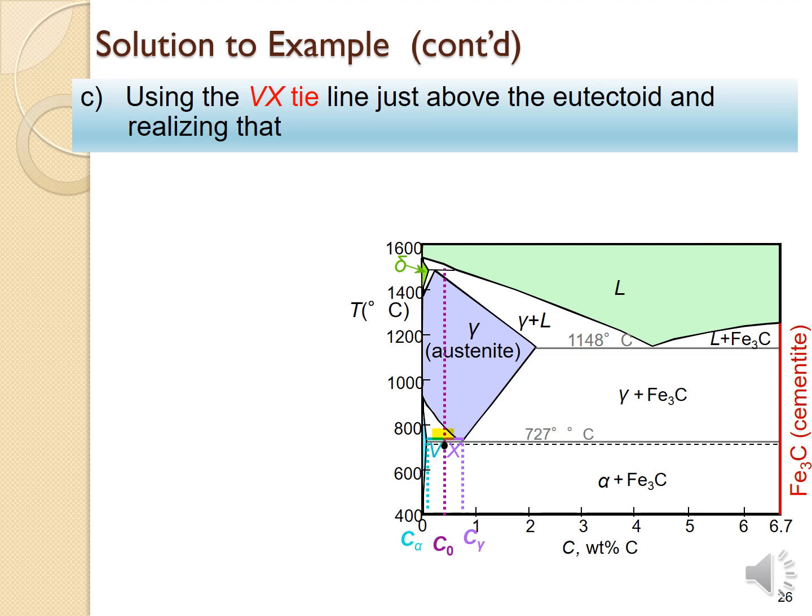Because during the eutectoid reaction, all of the austenite will transform into pearlite, and all the pro-eutectoid ferrite doesn't change at all. That will make our calculation much easier, which means we just need to calculate right before the eutectoid reaction.